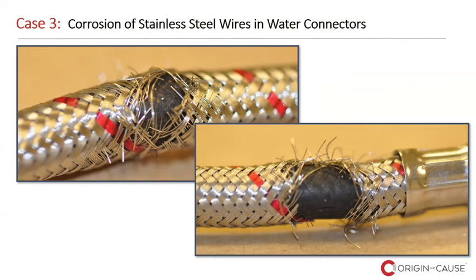This is much harder to see by visual inspection alone. It typically occurs as a result of some of the chemicals that get in contact with the surface of the wires. And the third one that I see, and it's very common here, is stress corrosion cracking, which shows as cracks that grow into the wires. And I will be showing a little more of these in the next few slides.